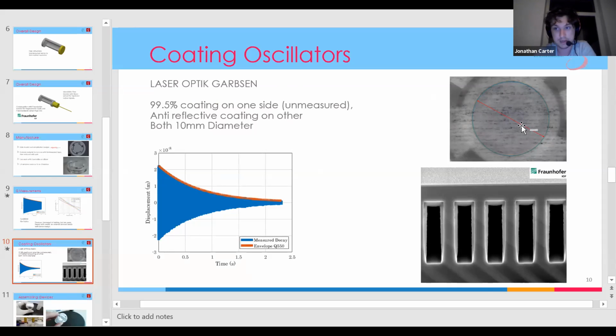We got the devices back and measured the quality factor again just to check that everything was okay. And we discovered that we'd actually degraded the quality factor by more than a factor of 20, down to about 550. Which was quite a shock. We really weren't expecting that. We were hoping that this would work pretty easily. We really didn't have any idea why that happened.